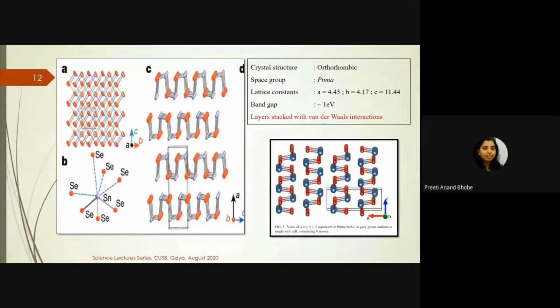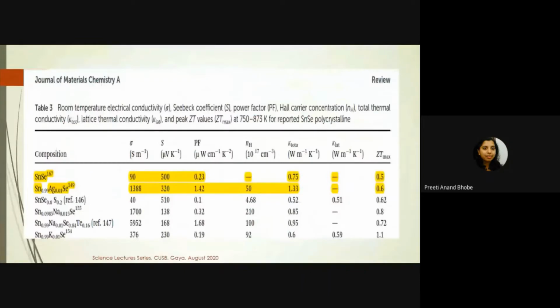We were like, oh, very good, wonderful. We have a single crystal which is showing such a nice thermal conductivity and it will revolutionize our thermoelectrics. But that does not happen, because when you try to make a polycrystalline form of this material, the polycrystalline ZT is around 0.5, like shown here. Though the single crystal is showing a ZT of around 2.5, in polycrystalline form it is coming down to something like 0.5.